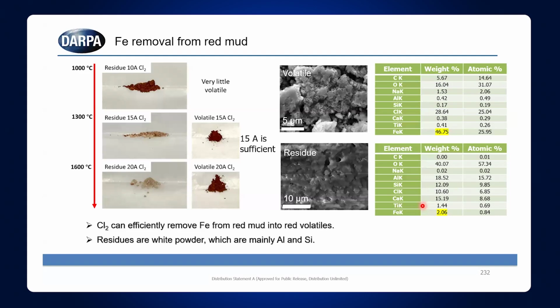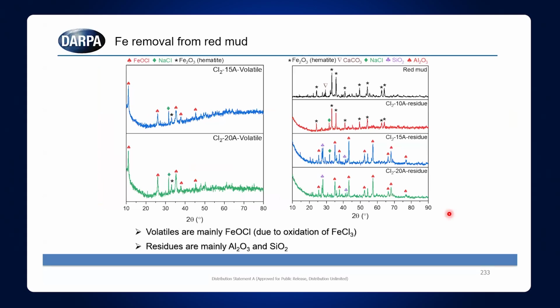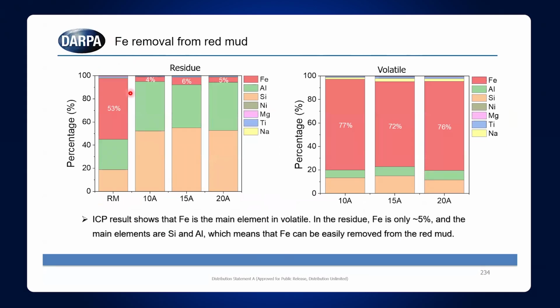And so you can see that at 15 amps, it was sufficient to reduce the iron. This was 46 weight percent to 2 weight percent. And this is the spectra that showed that you can get these out. But the bottom line is here. This is the red mud. This is all the iron that's in the red mud. After you flash it, say at 10 amps or at 15 amps, you bring it back down to about 5% iron. So there's only about 5% iron left in this at the end of it. And that's good enough for them to now do the separation.